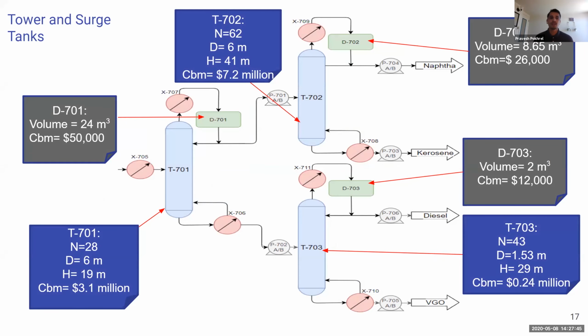Next, I'm going to be talking about towers and surge tanks. We had a total of 3 towers in our system, with tower 702 being the most expensive of all, with a CBM of $7.2 million. The total number of actual trays was 62, with a diameter of 6 meters and height of 41 meters. And the third tower, tower 703, was the least expensive of all because of the very low flow rate going into it. Since more than 95% of our VGO was already reacted, we thought about getting rid of it, but to maintain the higher purity of diesel, and since the CBM cost was just a fraction of the total tower cost, we went ahead and kept it in our system.